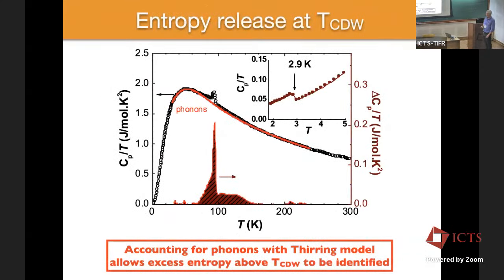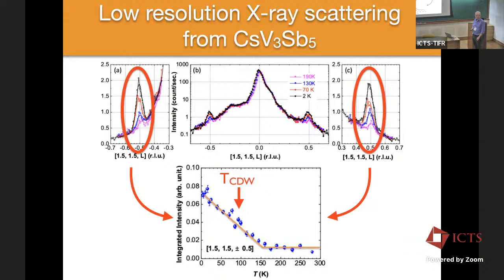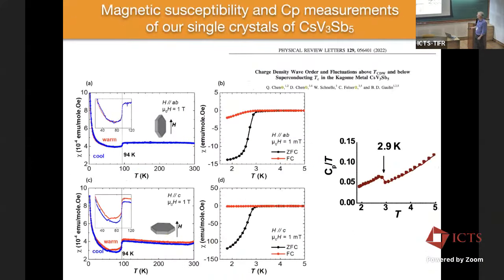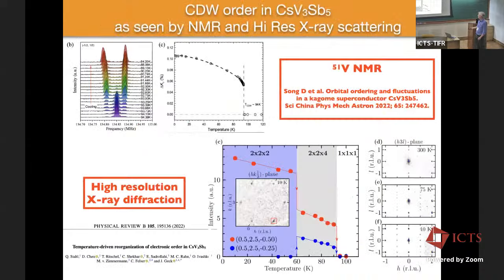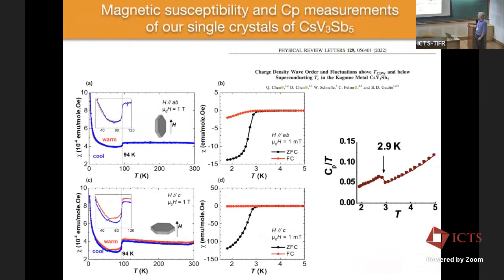Okay. Yep. So this is reproducible from sample to sample of the samples that we've looked at, yes. But the samples that we've looked at are all from the same batch. So this is the high resolution measurement on the same samples, or samples from the same batch rather. And from exactly the same samples, this is the susceptibility, which shows the anomaly at 94 Kelvin and doesn't show anything above that, right?